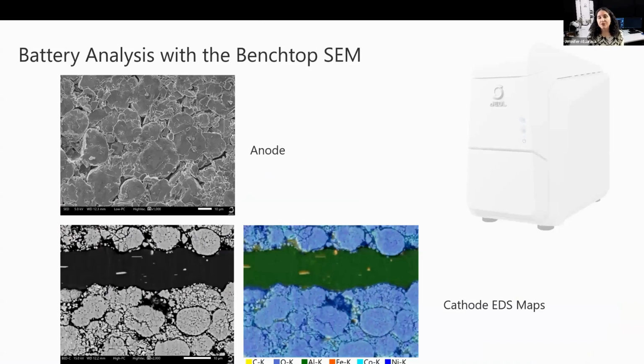Here's just a quick overview of some battery data that was acquired with JEOL's benchtop system. It's incredibly easy to use, it comes at a great price point, and can be quite useful for the characterization of battery materials. In the top image, we show an anode material acquired using the secondary electron detector at low voltage to highlight the surface structure. Below it is a backscattered electron image from a cross-section of a cathode, highlighting the composition contrast between the cathode material and the current collector.